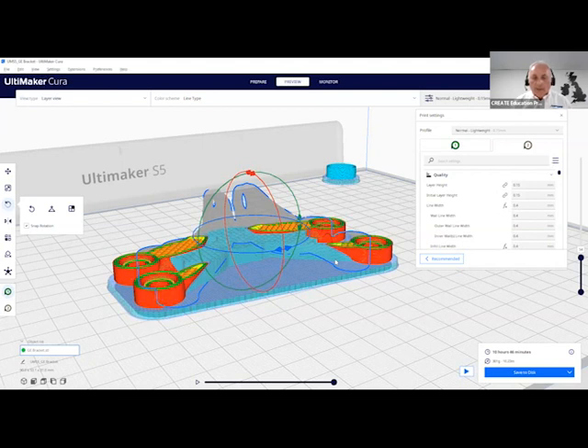And the plate is now shrinking at the same rate in the contact areas to the part as the part itself. Because they're now shrinking together, there shouldn't be any drag and there shouldn't be any distortion of the geometry. Now, you can print some parts and get away without that shrinkage plate. It's a matter of experience after a while, whether you need it or not. When you first engage with this, it's a good play-safe to stick with this.